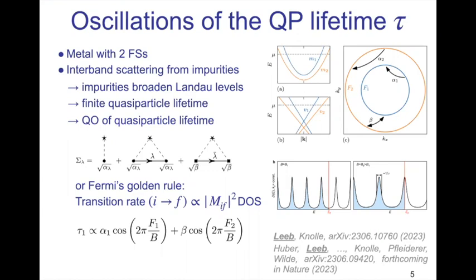So when you look at the lifetime of the first band here, you will see that you get oscillations with the same frequency as this band generates, with an amplitude set by alpha, so by the intraband processes, whereas you also get oscillations with the respectively other frequencies, so with the frequency of the other band. And the amplitude of that is set by these interband scattering processes.